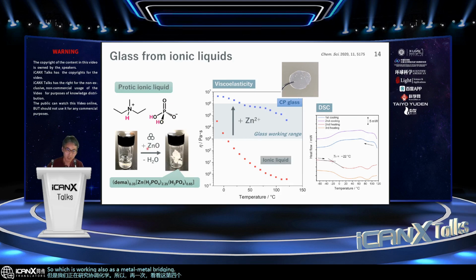So just simply, we do that reaction with zinc oxide, just by grinding here, okay? And then immediately we can get this glassy solid, which we expect to be a soft solid showing pretty high proton conductivity. So some of the properties are shown on this slide.